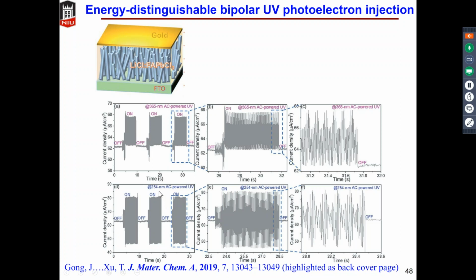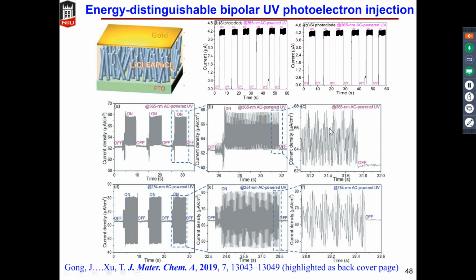However, when we changed the UV wavelength to 254 nanometers, we found that the photoelectric current oscillates across the baseline. This is very strange, because the intensity of light changes, and that causes the oscillation of your photocurrent, but there's no phase inversion of the intensity of the light. So why would the photocurrent decrease below the baseline? This puzzled us. Meanwhile, we also tested silicon-based photodetectors, photodiodes. They don't show this behavior.